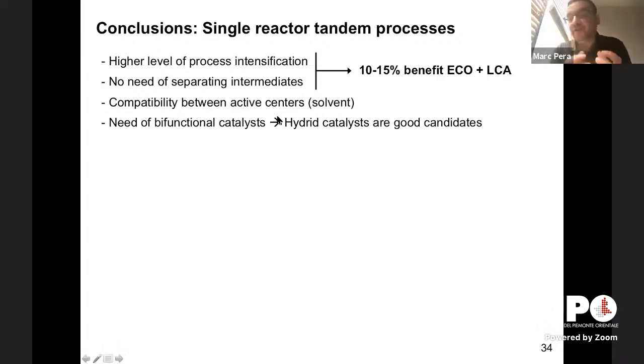But of course, in terms of science, the key point here is to design real bifunctional catalysts, avoiding antagonistic effects between the two different centers, acid-base, redox, redox, depending on the kind of catalysis you want to develop. And for that, for sure, hybrid catalysts, such as those that we develop in multi-2-HiCat, are ideal for that because we can tune very well the distribution of the sites and the compatibility between them.